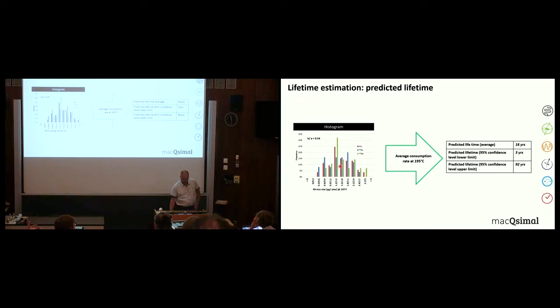So if we look now at the histogram, which shows us the rubidium loss rate in micrograms per year at 195 degrees, we see that we have here the biggest peak, which is in the interval of 1.2 to 1.5 micrograms per year. And from this consumption rate and from the relation I showed before, the temperature dependence, we can today say that we have a predicted lifetime of these cells of 16 years, but we have still a quite high interval of confidence with a lower limit of 3 years and the upper limit of 82 years.